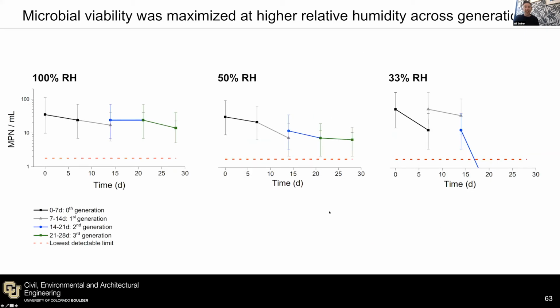This is just to show you that through the parent and child generations, the bacteria stayed alive if we kept the humidity above a certain threshold. So here is just a measure. Most probable number is a measure of how many bacteria are alive inside of the material. So obviously, if we kept the humidity relatively high at 100%, all of the bacteria survive through the parent, first, second, and third child generation.